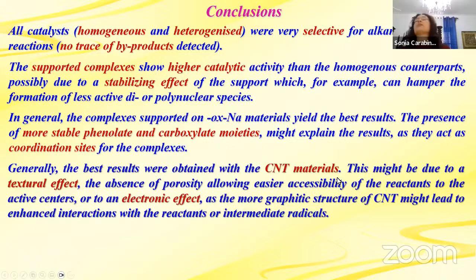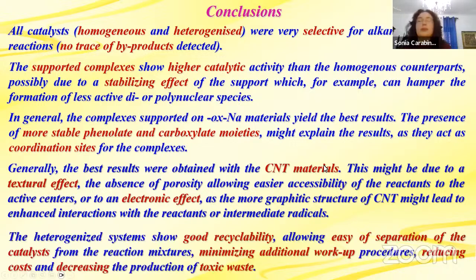And also the best results were obtained for the carbon nanotube materials in general, and it might be a textural effect. For example, these materials are tubes, so they have no porosity, okay? So it might allow easier accessibility of the reactants to the active centers, or else an electronic effect because of the graphitic structure, that might enhance reactions between reactants and intermediate radicals. We don't know, it's just some hypothesis.